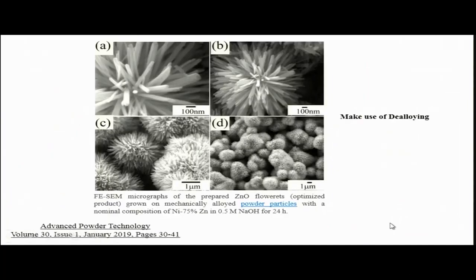Here is a nice picture made at lab scale: nanorods of zinc oxide produced while de-alloying Ni-75% Zn in 0.5 M NaOH. The alloy was made via ball milling and dipped in 0.5 M NaOH for 24 hours. After doing that, we got a nice flower-like structure — each particle became a flowery structure which we call zinc oxide flowerets.